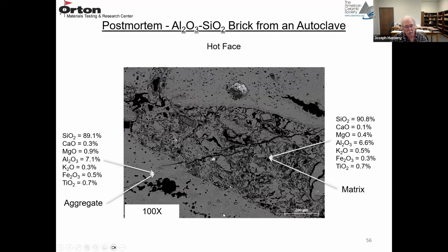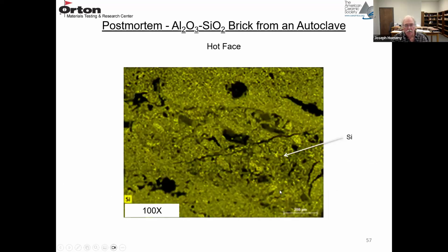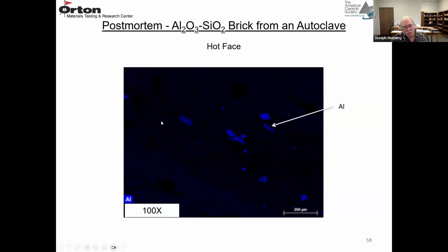So a little bit higher magnification. Here's a coarse aggregate. Here's another coarse aggregate, and then you have your matrix region. So they're both very similar at this point. They're both about 90% silica and about 7% Al2O3 alumina, and your typical impurities. Again, if you map silicon, it's pretty uniform. So the coarse aggregate was probably made from a clay, and it was probably bonded with the same clay-based material. So that's why it's uniform. There's some alumina enriched fines in the matrix.